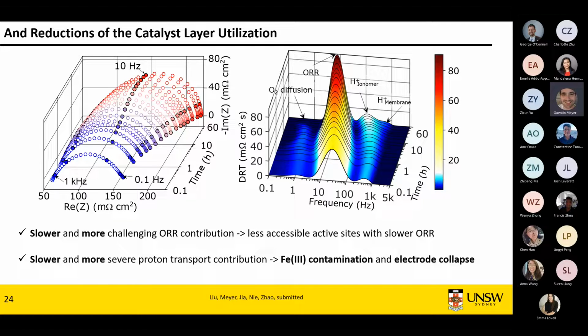Initially, you just have proton transport as one peak. And then as the cell degrades, it splits into two peaks, one proton transport in the membrane, and one proton transport in the ionomer of the catalyst layer. What this indicates is proton transport becomes much more difficult in the catalyst layer. There are two likely reasons. The first one is you have iron demetallation. So your iron ions are going to contaminate your ionomer, reducing proton conductivity.